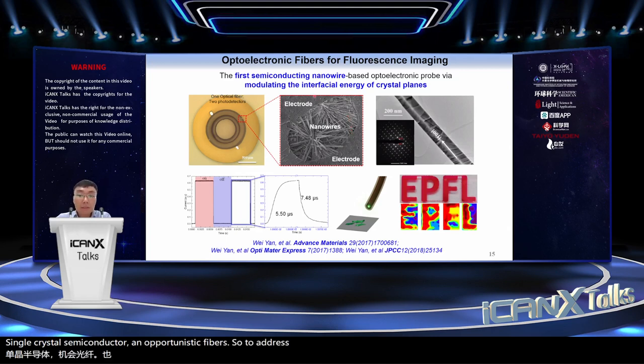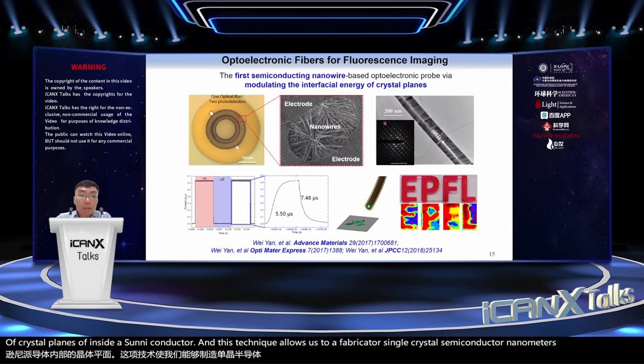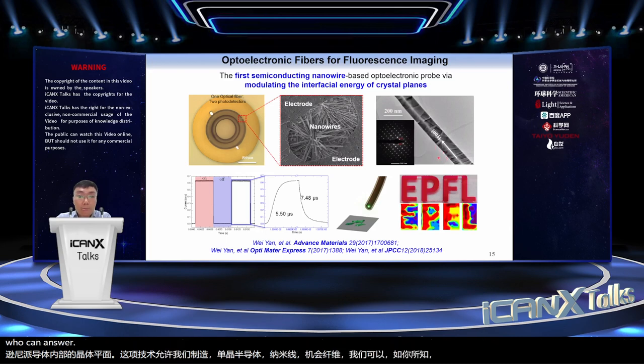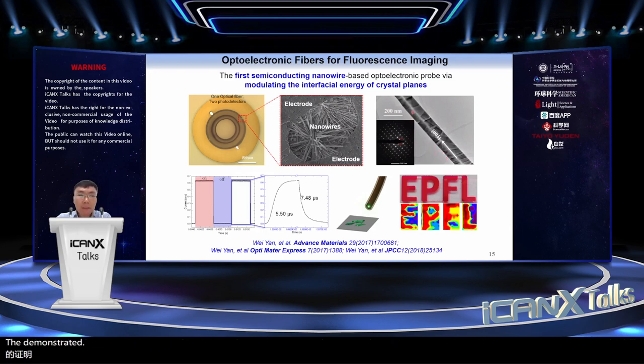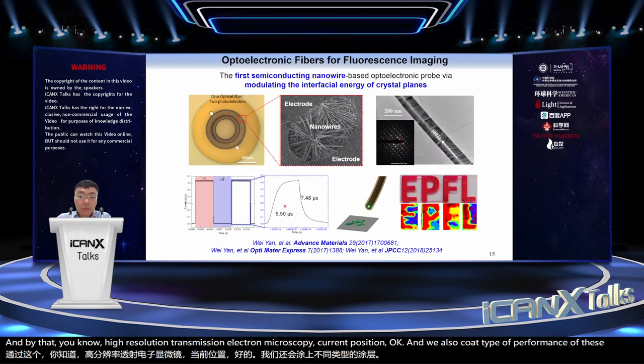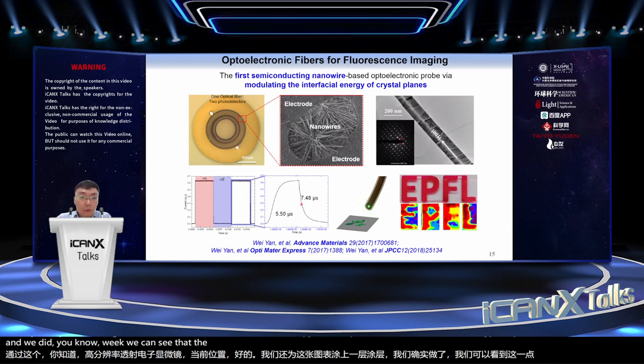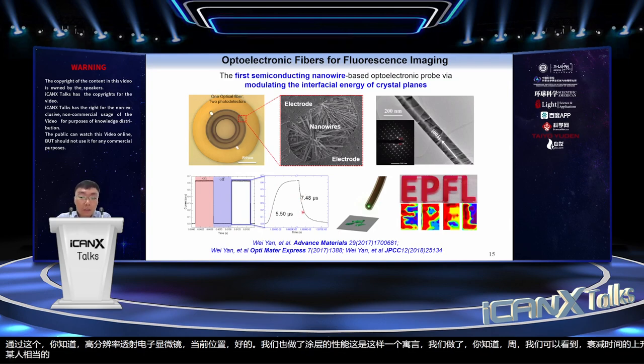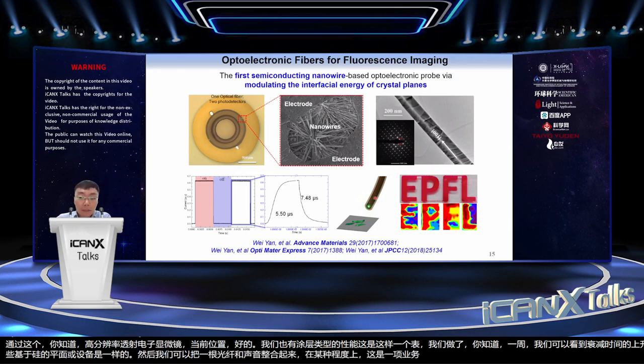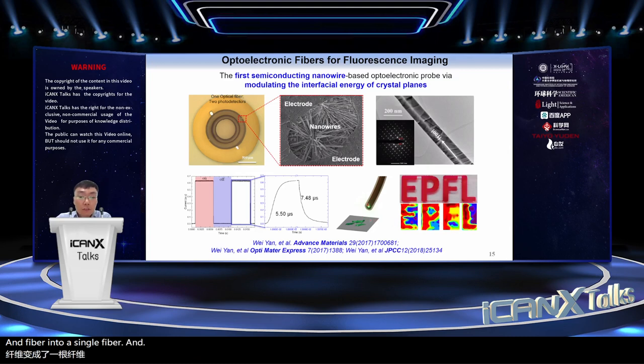To address this issue, we proposed a strategy of modulating the interfacial energy of crystal planes of the in-fiber semiconductor. This technique allows us to fabricate single crystal semiconducting nanowire-based optoelectronic fibers, as demonstrated by the high-resolution transmission electron microscopic characterization. We also characterized the performance of such a fiber, and we can see that the rise and decay time is on par with some silicon-based planar devices. Then we can integrate one optic fiber and two nanowire-based photodetector fibers into a single fiber, and we use such a hybrid fiber